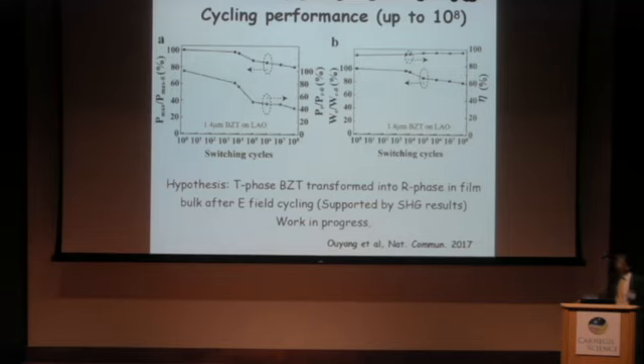And here is the cycling performance. We cycle the film up to 100 million times. You can see here is the change in polarization. So you can see the maximum polarization actually only changed by 20%. From after 100 million times, the maximum polarization becomes 80% of the initial one. But what changes most is the remnant. It becomes only 40% of the initial.